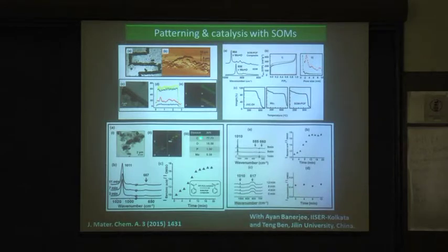and that is what we did. So, what we did is we did a simple reaction, benzaldehyde to benzoic acid, and we catalyzed it using this type of dispersion as well as the pattern chip. Now, when we do it on the dispersion, we get a sigmoidal type curve. That means it is a heterogeneous type catalysis, right? And then we looked at the phase transition. For example, you can see from Raman spectroscopy, of course, you have a similar kind of phase transition, which is marked by the shifts in the Raman bands.